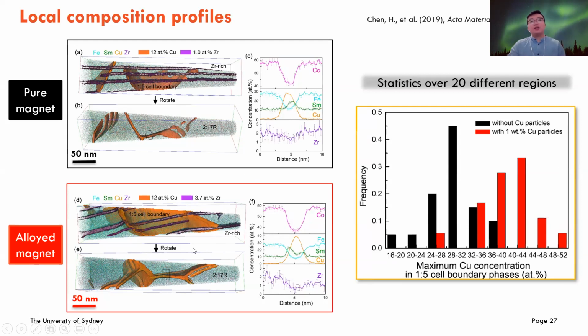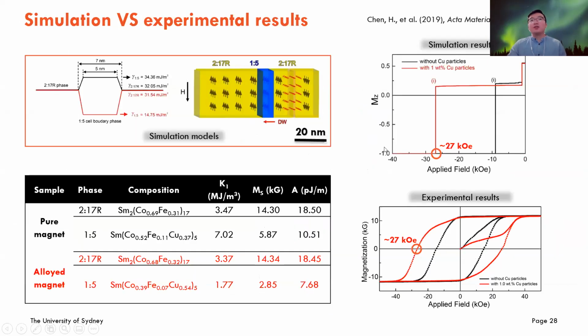But we actually observed the copper concentration varies along different 1:5 cell boundary phases. Then we do the statistics and grab the information more statistically. We got the distribution of the maximum copper concentrations in this phase, and using those values, we construct the models. You can see the models here. The blue is the 1:5 phase, and we're varying the thickness and also varying the concentration here. Based on different concentrations, we again simulate the K1, MS and the exchange coupling constant based on our atom probe results here. And we get the simulation results.